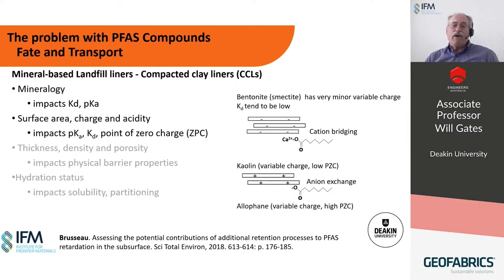However, allophanes are very rare in Australia. Instead, Australian soils are rich in kaolins, which, while having variable charge, generally have a low point of zero charge. So the pH is more like 4, at which they are net zero. So you have a greater chance for some PFAS compounds to be present in both the anionic and the free acid form when in contact with kaolins.